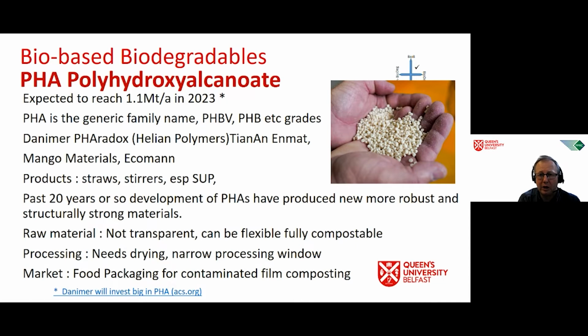This recent growth of PHA has evolved due to the development of more robust raw material grades, which can withstand the intensity of polymer processing, just to give you a much more stable process. The main advantage of PHA is that it is fully compostable, and it can be flexible or rigid. However, like PLA, sorry, PHA is a polyester, and it requires very efficient drying protocols, but also requires good extrusion controls, such as temperature controls, due to a very narrow processing window.